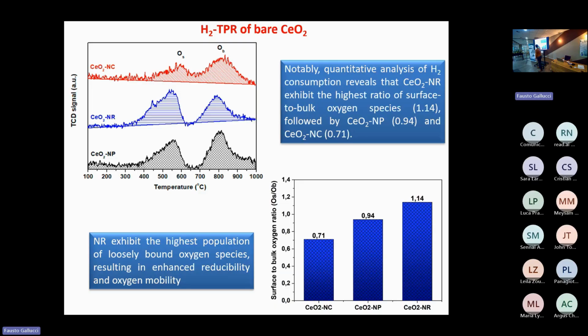Two peaks are observed. The first one is related to the reduction of surface oxygen, whereas the second, at higher temperatures, to the bulk oxygen. Notably, quantitative analysis here revealed that the surface to bulk oxygen ratio follows this order: nanocubes, nanopolyhedra, and nanorods. That is, nanorods exhibit the highest population of loosely bound oxygen species.